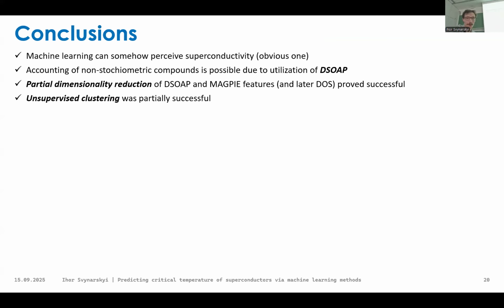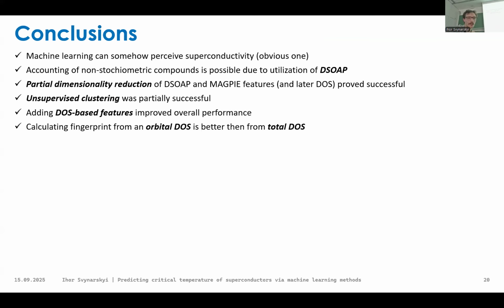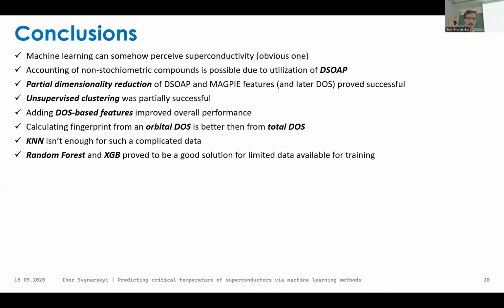Clustering was partially successful; adding those features slightly improved performance. Then, resolving on orbital DOS is better than doing it for the total DOS. So it seems physically explainable. Yeah, KNN failed for the data with DOS, it's for sure. But random forest and XGB were good in both cases, in data without DOS and with DOS.